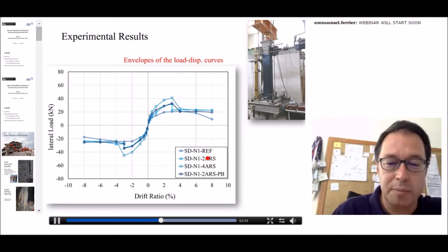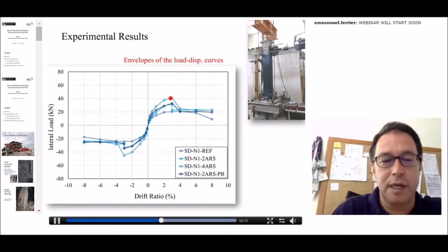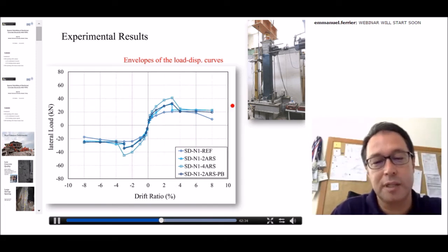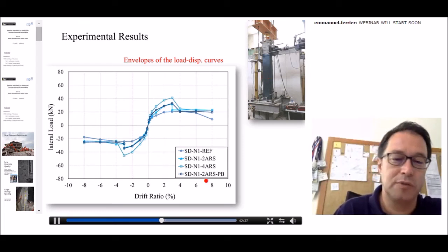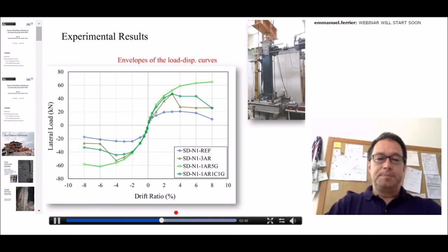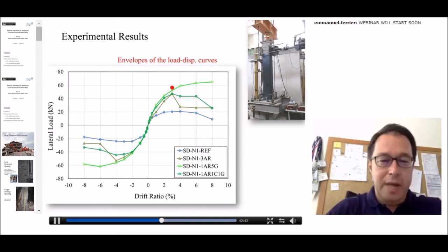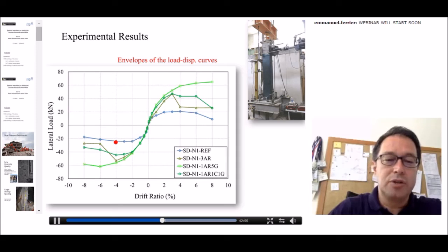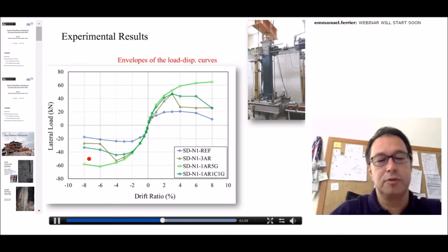In the case of the bar where we have additional anchors, we have again the degradation of strength, and then much more ductile behavior due to the presence of the transverse CFRP sheets. So, as I said, we applied different techniques, different materials, different applications like hybrid application, different AFRP, CFRP, GFRPs to make benefit of all of those. And as you see, if you compare the behavior with the reference one, we have a really significant increase in strength and, you could say, deformability, displacement capacity, through different usages of this kind of retrofitting technique.